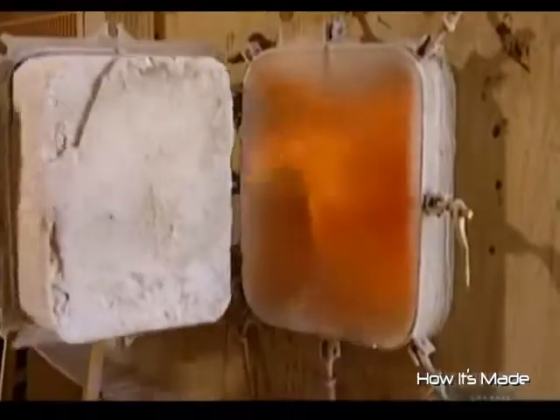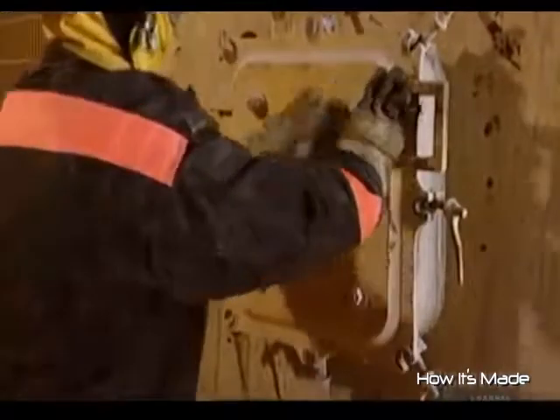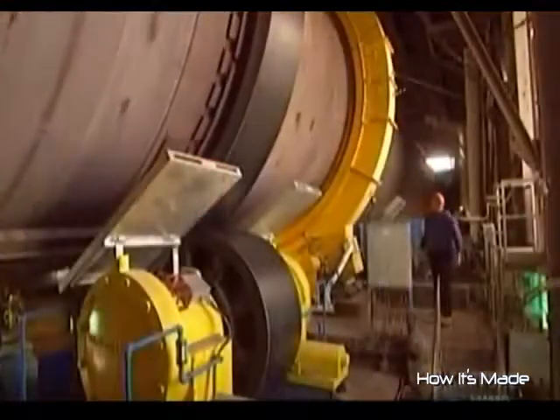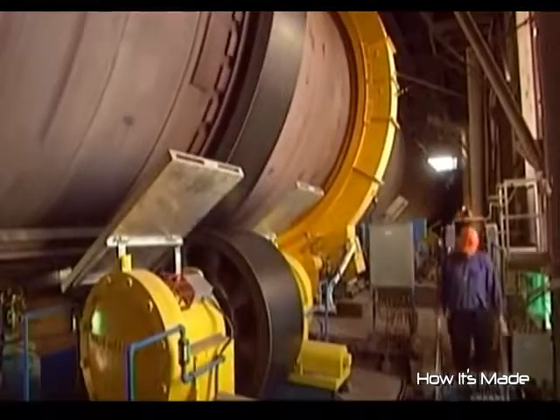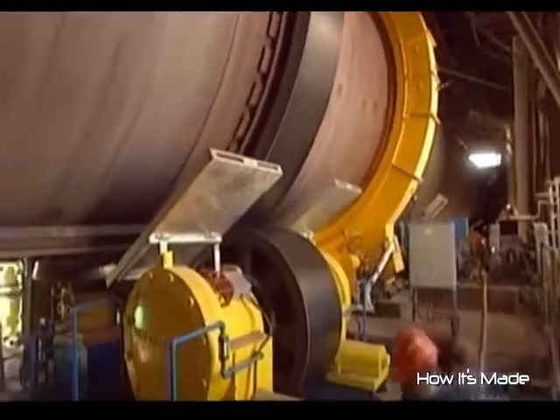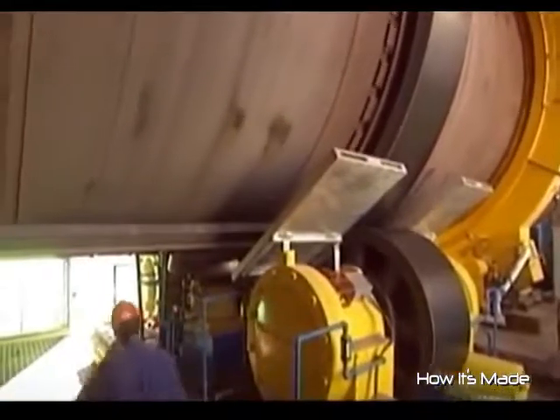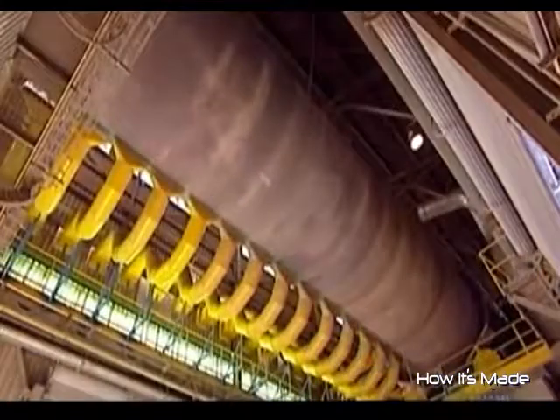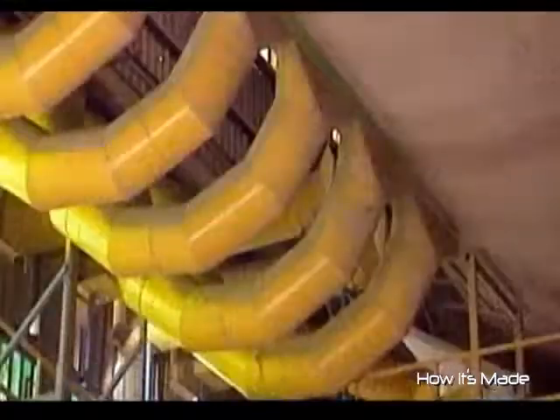The preheater is equipped with what's called a flash calciner. In about 5 seconds, it removes 95% of the carbon dioxide in the powder through a chemical reaction. This isolates the lime, which is the most important element in cement. From there, the powder moves into a rotary kiln, a huge cylindrical furnace.